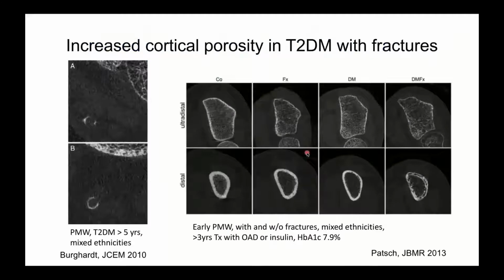So let's go to diabetes, right? Because the whole discussion about porosity started about 10 years ago with the observation, first of all, by Burghardt, that there was increased porosity in diabetic bones. So I remind you that it was a relatively small group of postmenopausal women with type 2 diabetes for more than 5 years and of mixed ethnicities. And he described this cortical porosity.